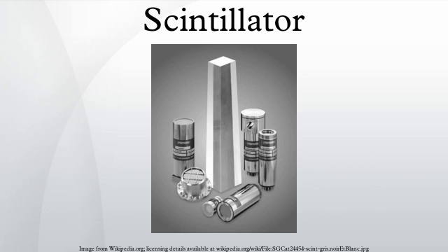The singlet excitations immediately decay to the S1 state without the emission of radiation. The S1 state then decays to the ground state S0 by emitting a scintillation photon. This is the prompt component or fluorescence. The transparency of the scintillator to the emitted photon is due to the fact that the energy of the photon is less than that required for an S0 to S1 transition.